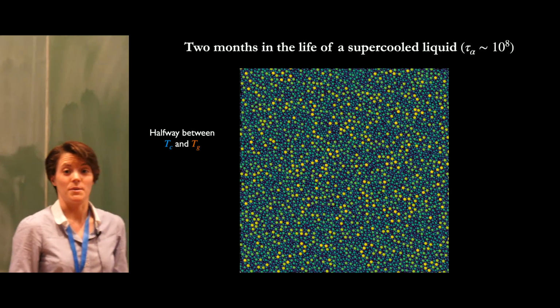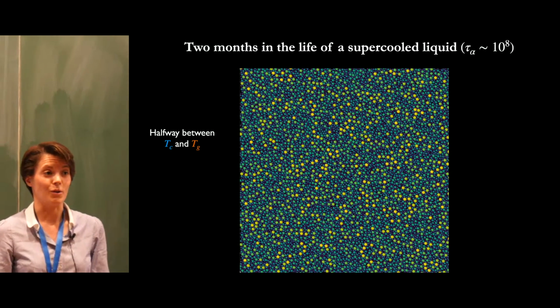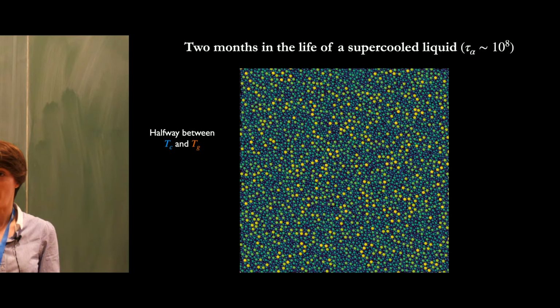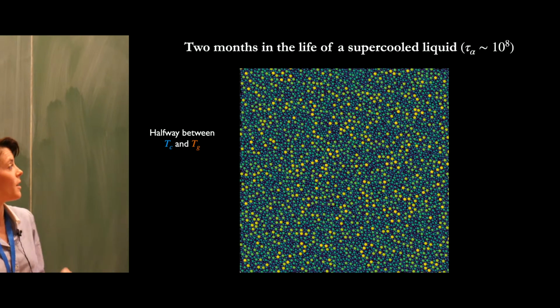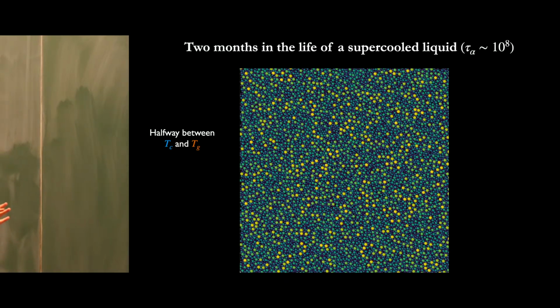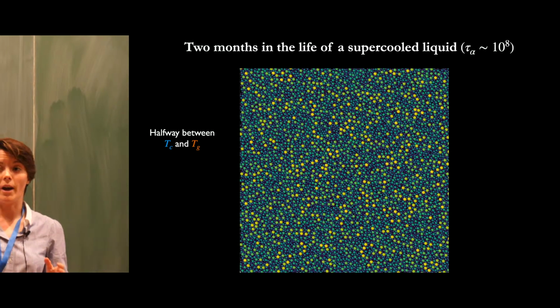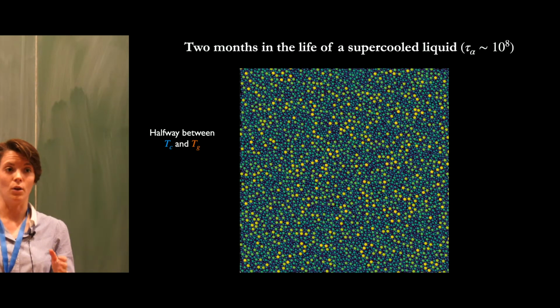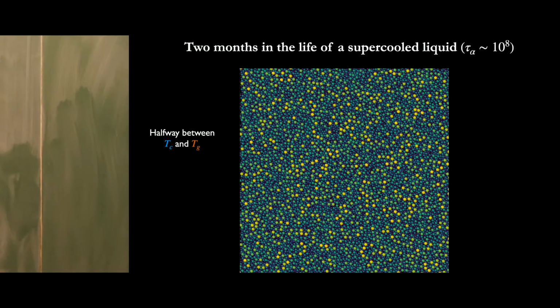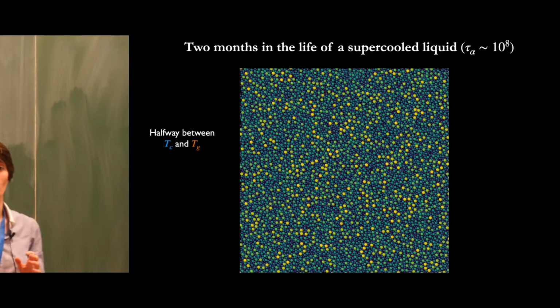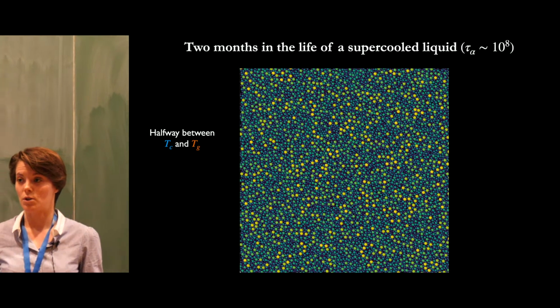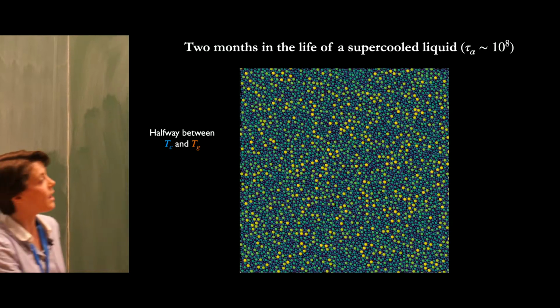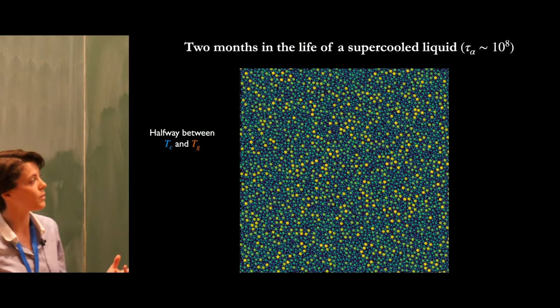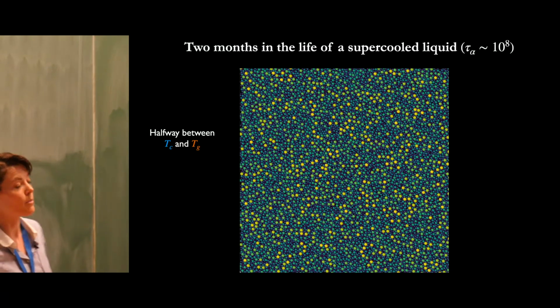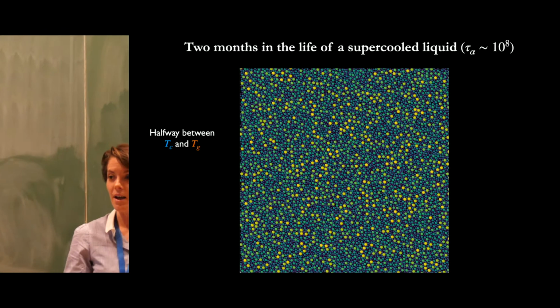But now we have computer simulation, so we can go beyond what experiments can do, and actually have microscopic insights into what's happening. Here I take one of the systems at the lowest temperature at which we're able to see 10 to the 8 tau alpha, and this still requires a 2-month simulation. In terms of timescales, we're roughly halfway between the mode coupling and the experimental glass transition, so really deep into supercooled liquid. This is the initial structure, where the particles correspond to the size of the particle, they're polydisperse, and I think that no one here by eye could predict or tell what's going on.